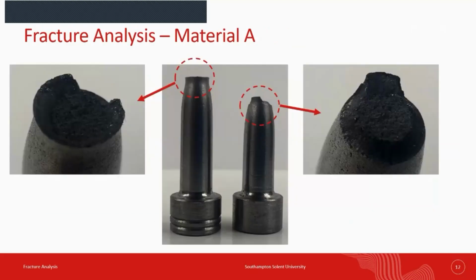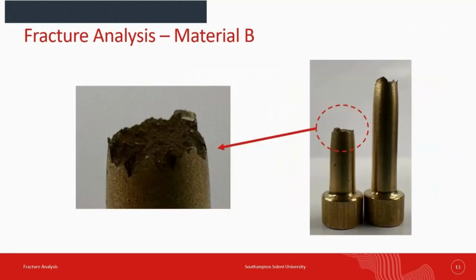In material A, we observed a classic cup and cone fracture, which is a clear indicator of ductile failure. A faint cup and cone shape is present, but it's much less pronounced than in material A. The tooth-like features around the edge suggest a mix of ductile and brittle behaviour. This aligns with the properties of brass, which has moderate ductility but can fracture more abruptly under certain conditions.